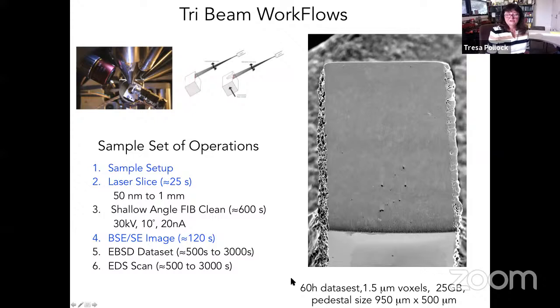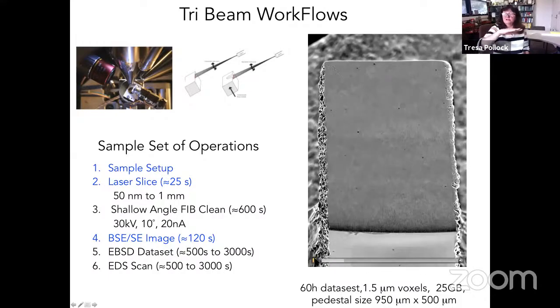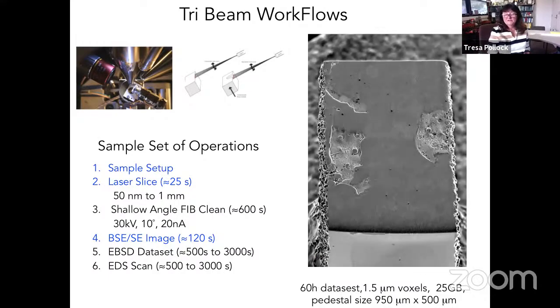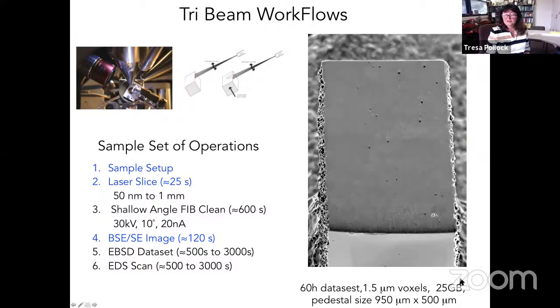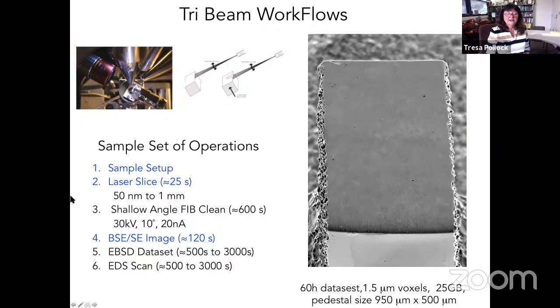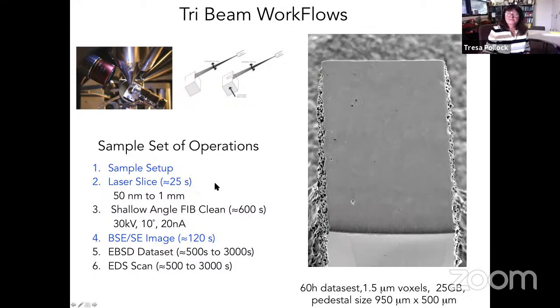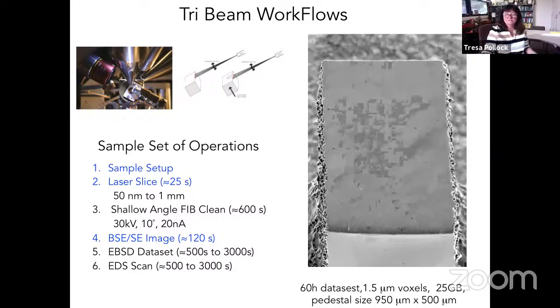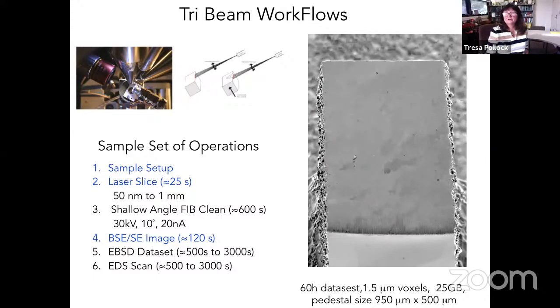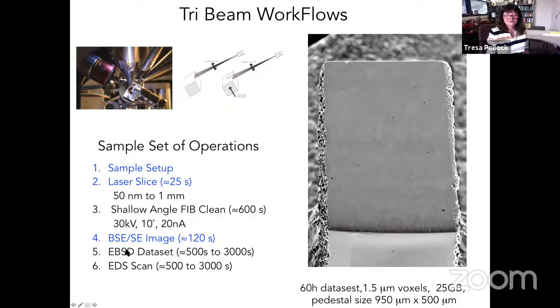So this setup shows the sample in the microscope. And as I said, we go at glancing incidence. And so this is really just an example about workflow. So you can see a sample here that's been 3D printed. And this data set that you're seeing layer by layer here has been collected over 60 hours. There's 25 gigabytes worth of information here. And each slice takes only 25 seconds. So the femtosecond lasers are very effective for speeding up the process of developing a 3D data set.